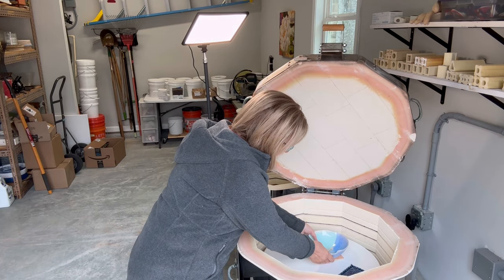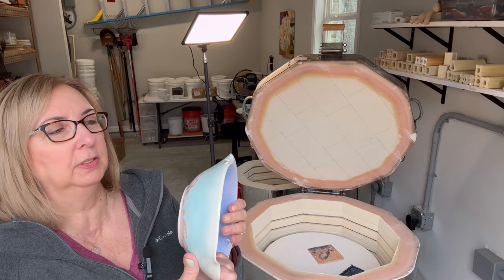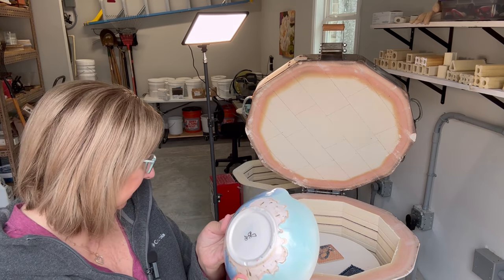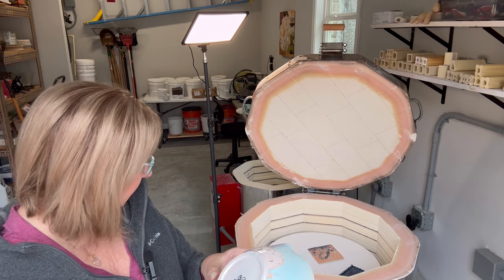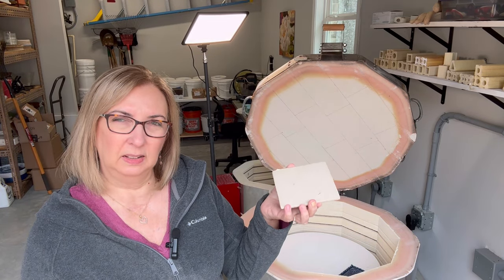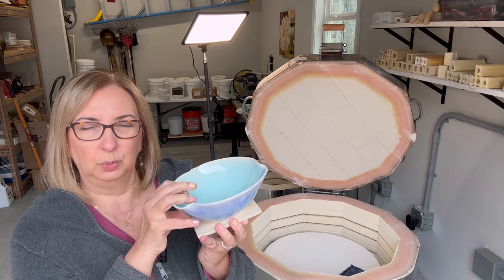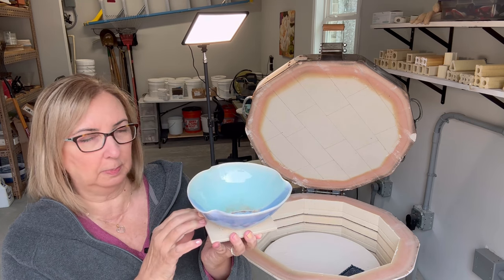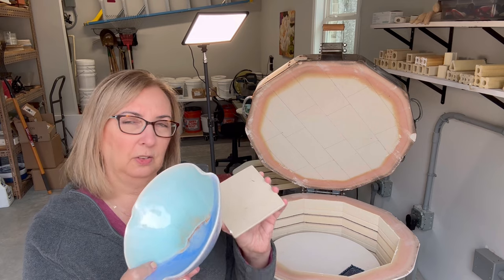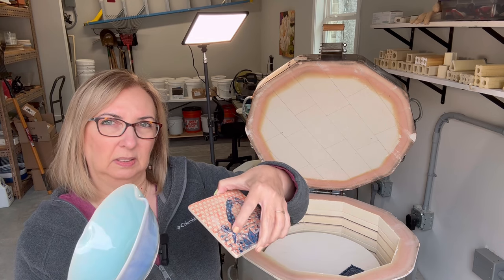So this is the test piece that I did — it's porcelain — and the colors are real pretty. I did half and half on this one. It plucked the bottom part a little bit because I was afraid it was going to run off the pot, but it didn't. What I did is I put it on a cookie that I had already used before, so it's porcelain and it's already vitrified. Porcelain is notorious for doing that plucking, especially over another piece like a tile of porcelain. I should have put kiln wash or alumina hydrate on this one, but I didn't, so it plucked a little bit.